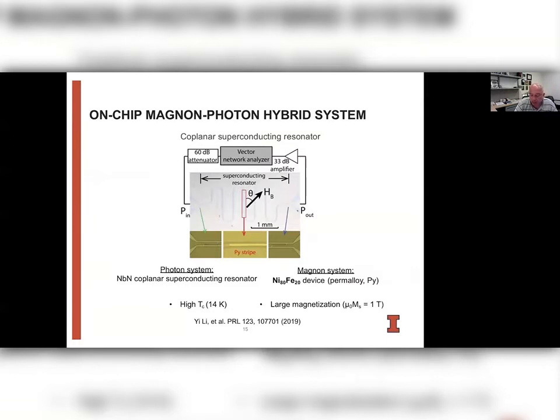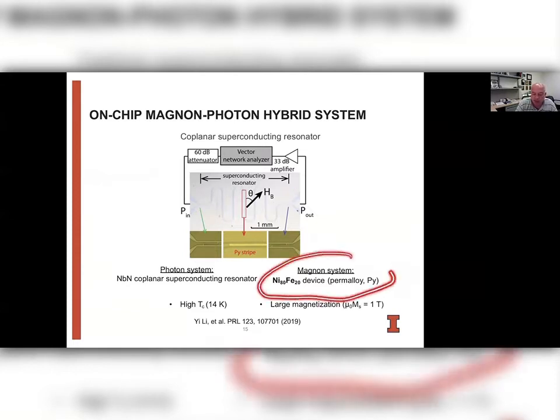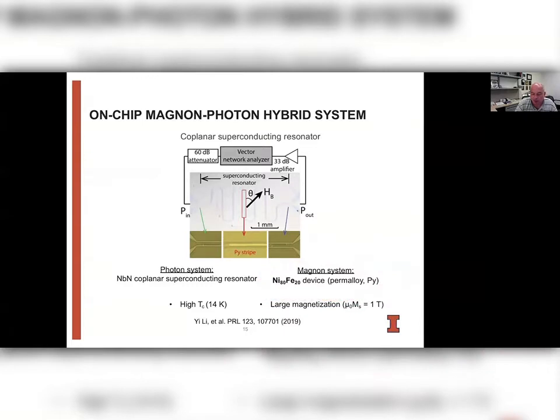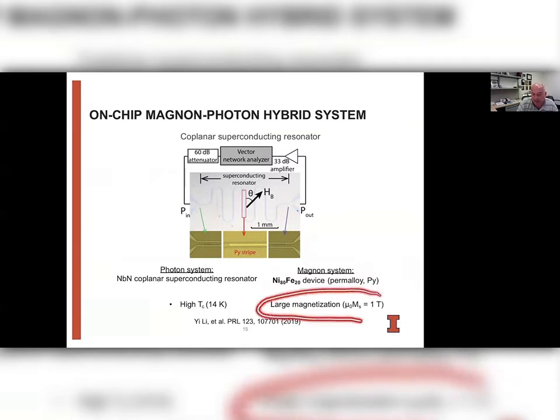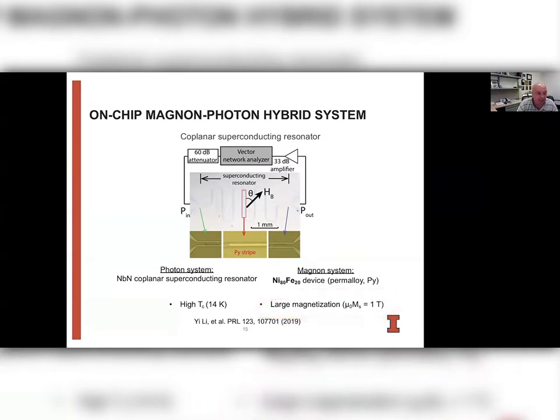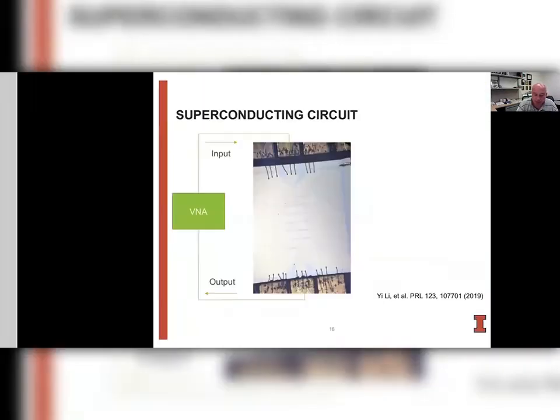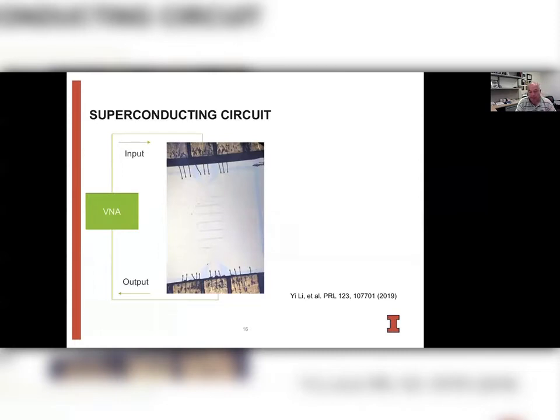At the same time, for the magnetic system, instead of yttrium iron garnet, which has been commonly used so far, we used a permalloy structure. And the reason for this is that since it's a simple metallic system, it's easy to process and integrate into our devices. But compared to yttrium iron garnet, it actually also has an advantage of having a relatively high saturation magnetization, which makes it easier to have stronger coupling. It has, of course, a disadvantage that the magnetization damping of permalloy is not as good as yttrium iron garnet.